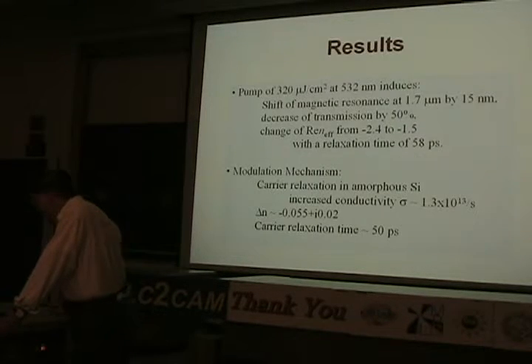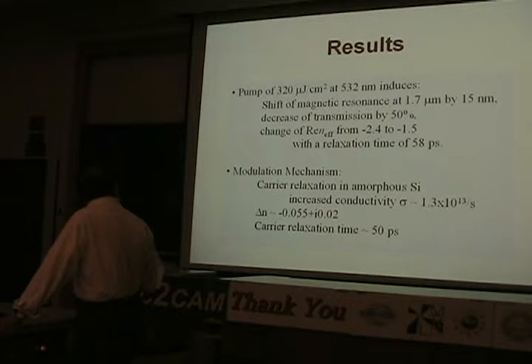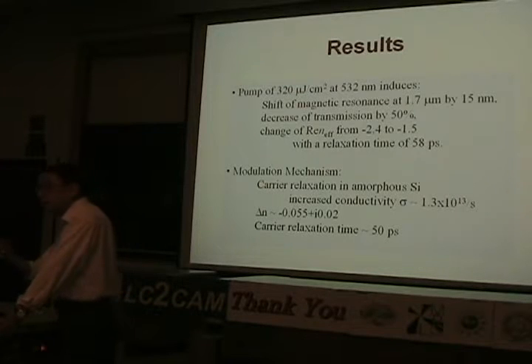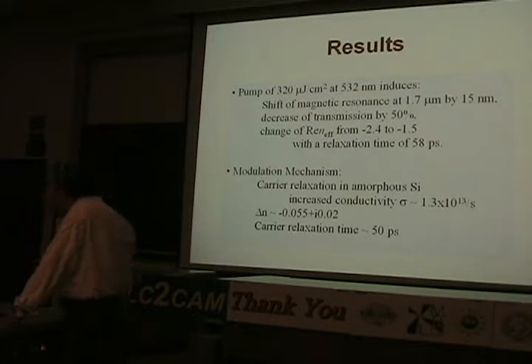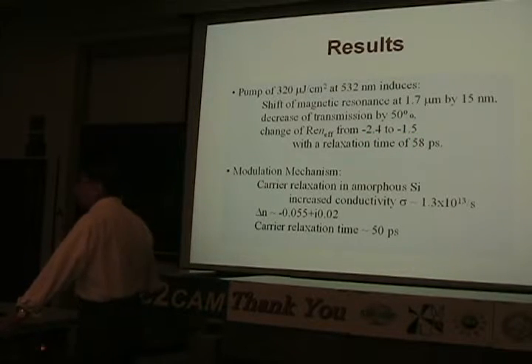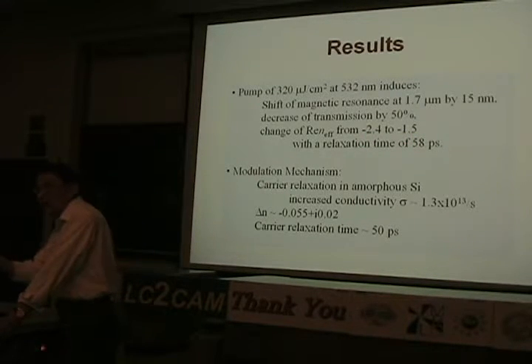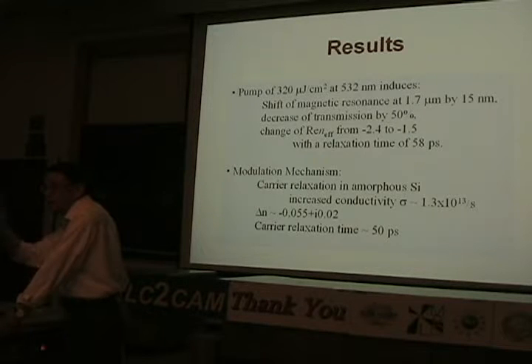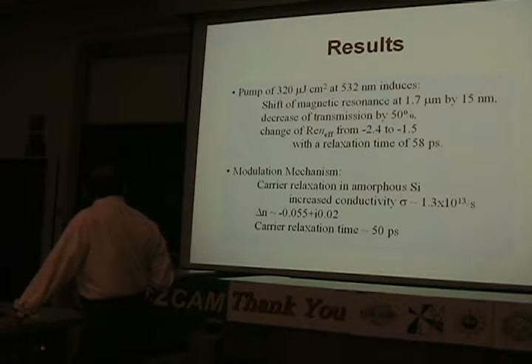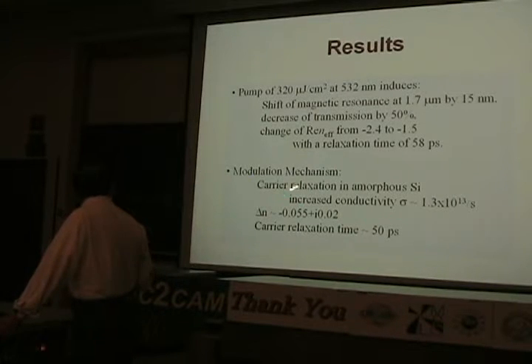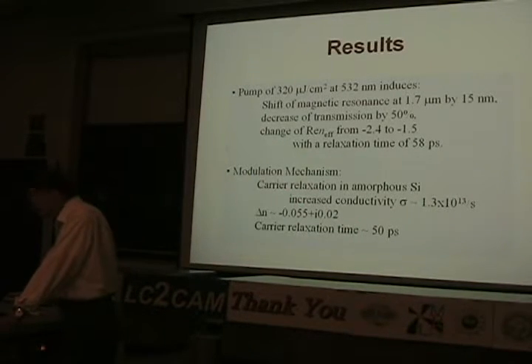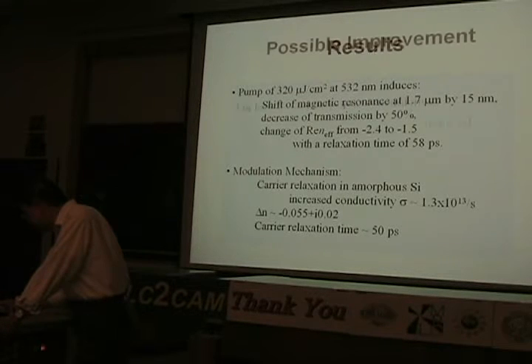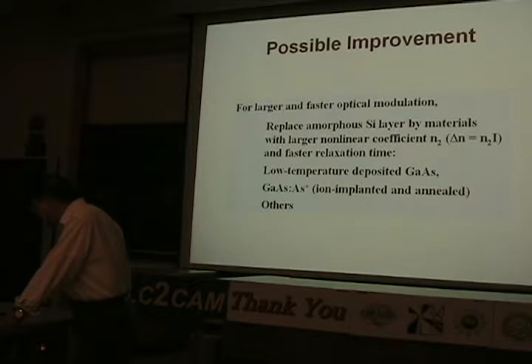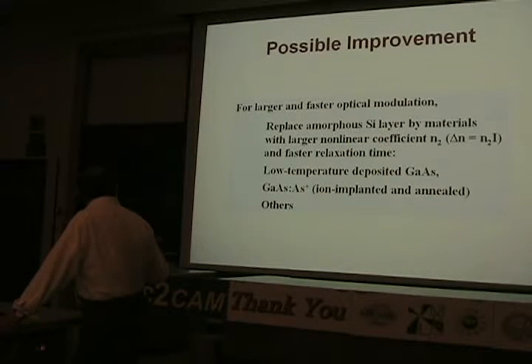So what we can see is indeed we can get fairly strong modulation on the refractive index. From minus 2.4 to minus 1.5, indeed this is a fairly large change, and it can shift the transmission quite a lot, especially if the medium can be thicker. And the mechanism, as I already said, is coming from the carrier excitation in the amorphous silicon. And the possible improvement I already mentioned: we can replace the amorphous silicon by materials with large nonlinear coefficient.